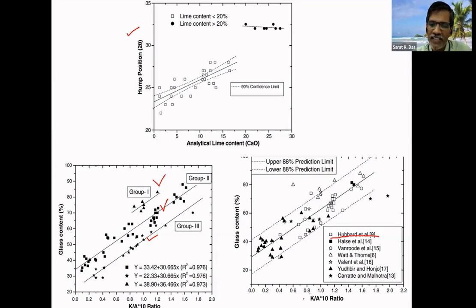So it's not only this ratio which is responsible to tell you the pozzolanic or amorphous phase quantity. Rather, there is something else at the same ratio of K/10, which was suggested by Hubbard et al. Something else is playing a role, and that could mostly be the efficiency of the plant, that is your grinding and so on. And the limitation of this data is that I have not added very recent data after 2015 or so. This data is whatever has been published, starting from the 1950s.